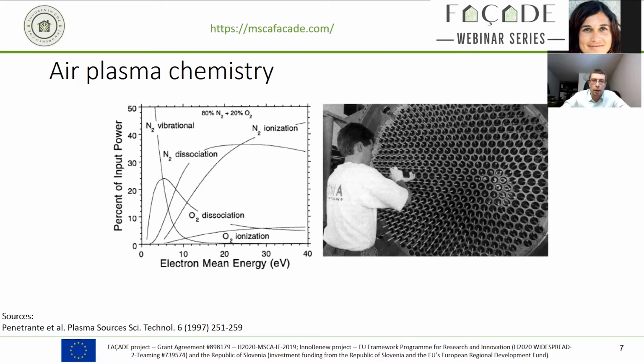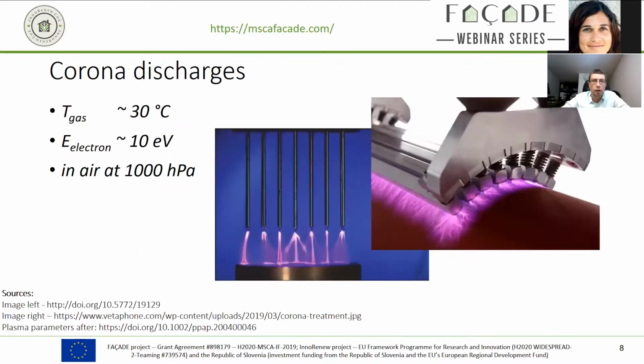And in air, the main gas species where interactions happen is oxygen, where the resonant transfer leads to dissociation of the oxygen. And so this is what we're seeing in this case, that the O2 dissociation is very efficient, particularly still in this region where our plasmas are actually working. And so this provides a very high energy efficiency for what we're putting into the discharge.